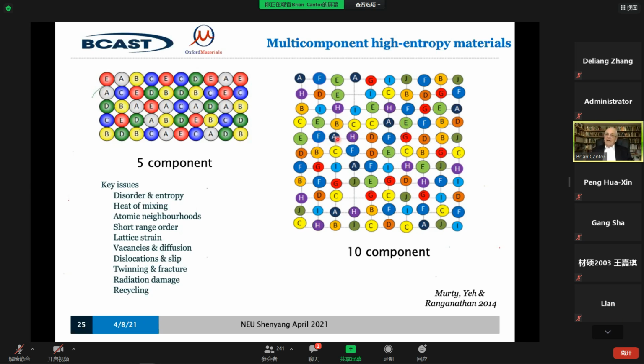Now, that is a remarkable thing, because if you have FCC copper, or pure gold, or pure nickel, every point is exactly the same. And even if you have a solution, like you add a little bit of aluminium into nickel, even if you add a little bit of carbon into iron, even if you add a little bit of tin into copper, only the occasional atom is different. So most of the atoms are the same. In this case, we've got a massive number of different local structures, partly because there's different atoms, A, B, C, D, E, F, and so on, but even every single A atom is different.